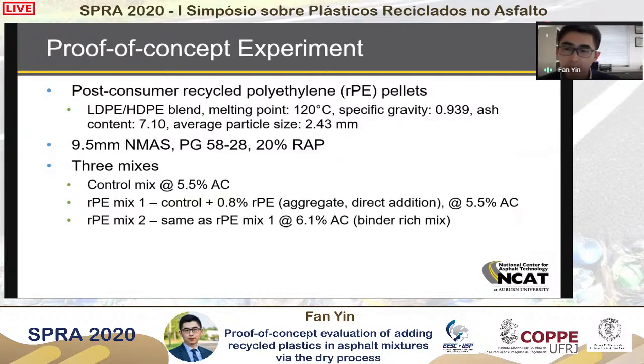The mix design we use is a very typical mix design that we have been using on the NCAT test track, a 9.5 millimeter surface mix with PG 58-28 binder, 20% RAP content, which is about the average RAP content used in the United States.